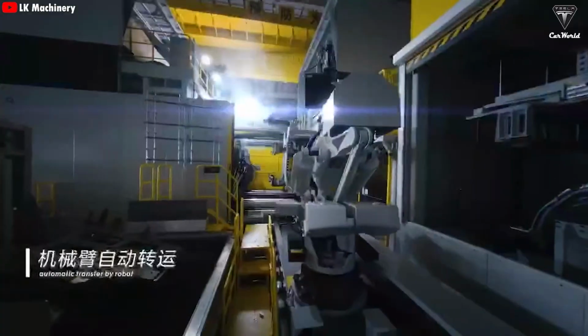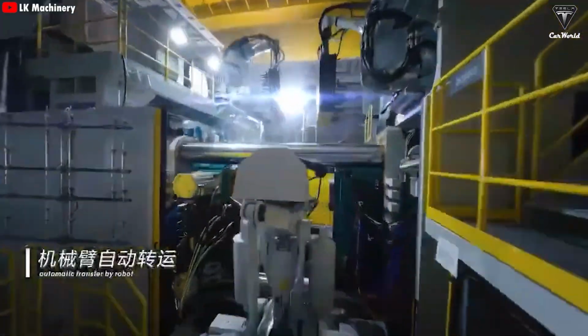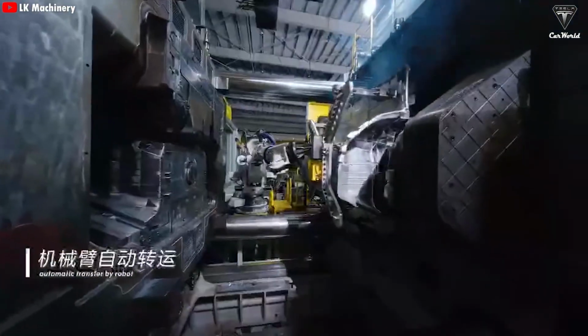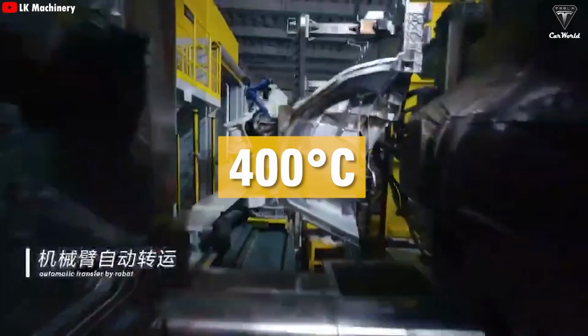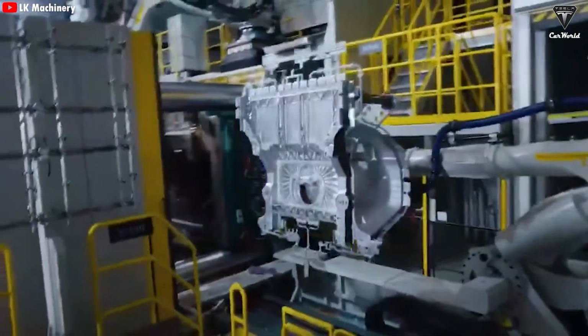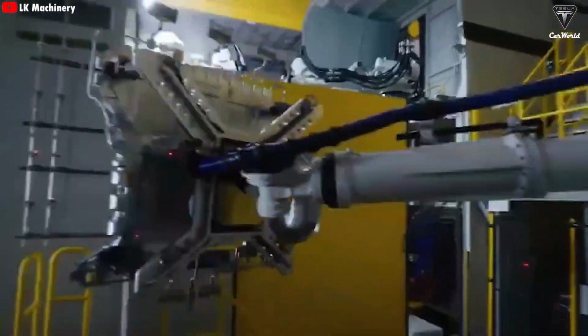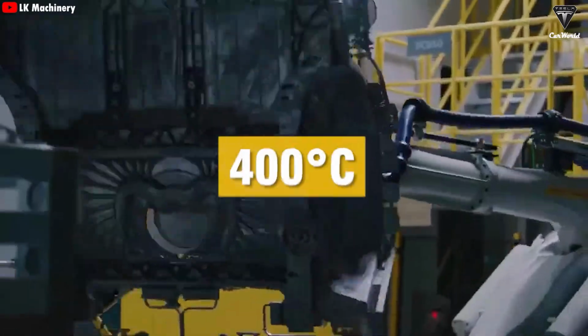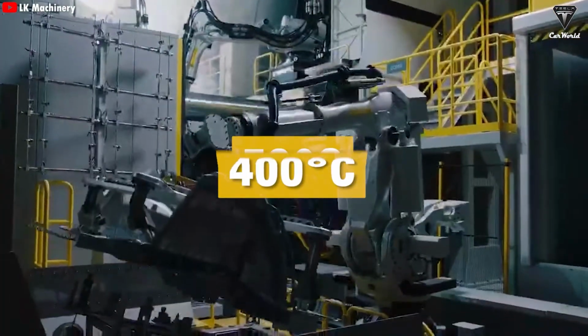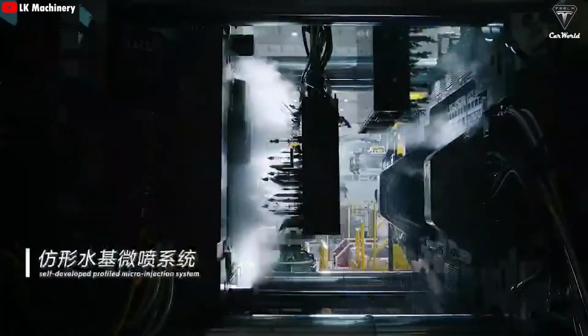After the aluminum is injected, it's left inside the mold until it solidifies. The casting is ejected from the mold at around 400 degrees Celsius. Then, the raw casting is placed into a cooling bath to quickly bring the temperature down from 400 degrees Celsius to about 50 degrees Celsius. This rapid cooling helps eliminate certain defects and enhances some of the material properties.